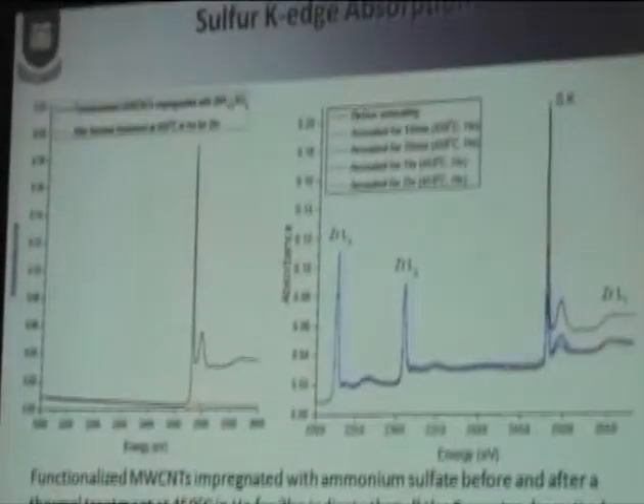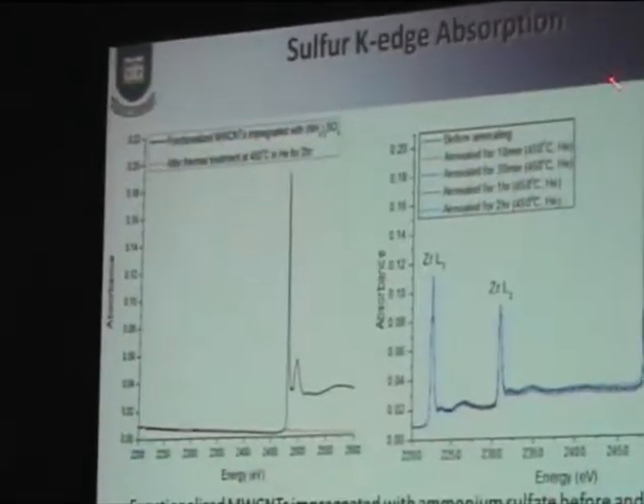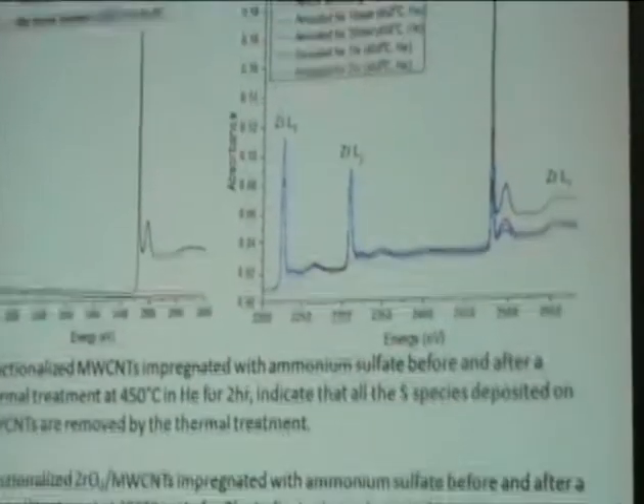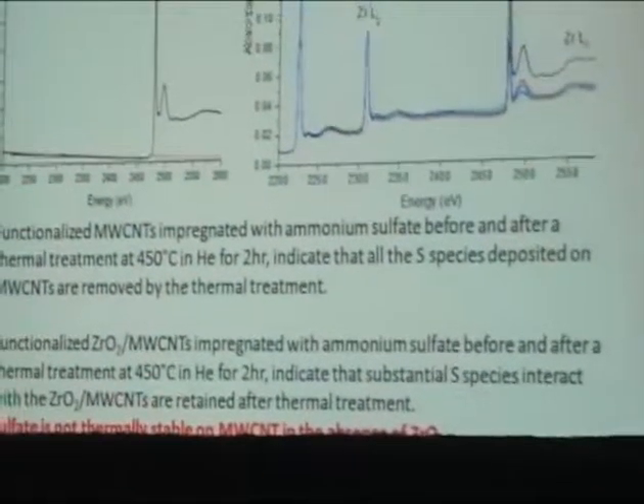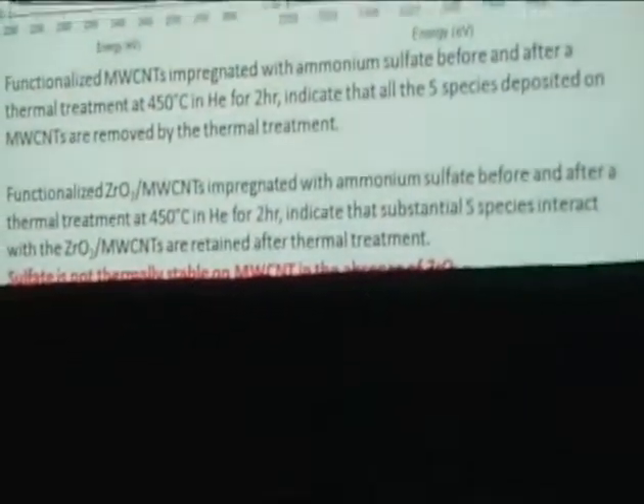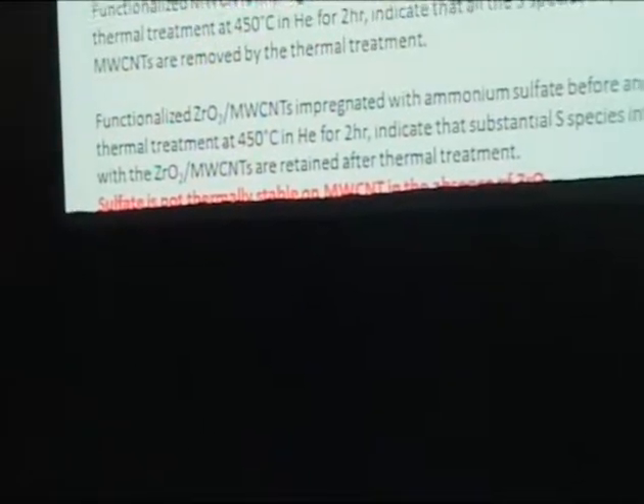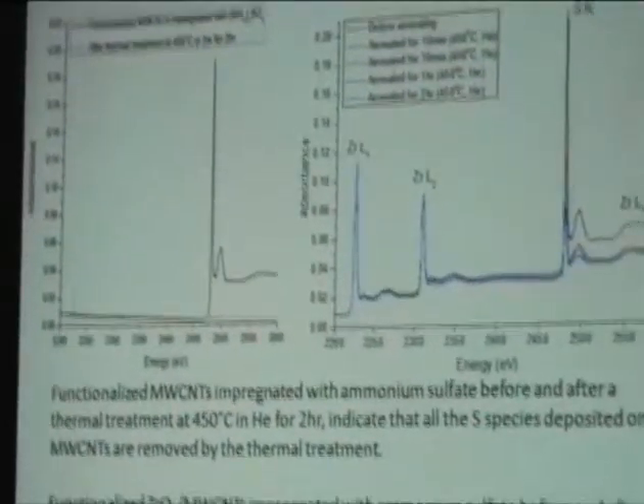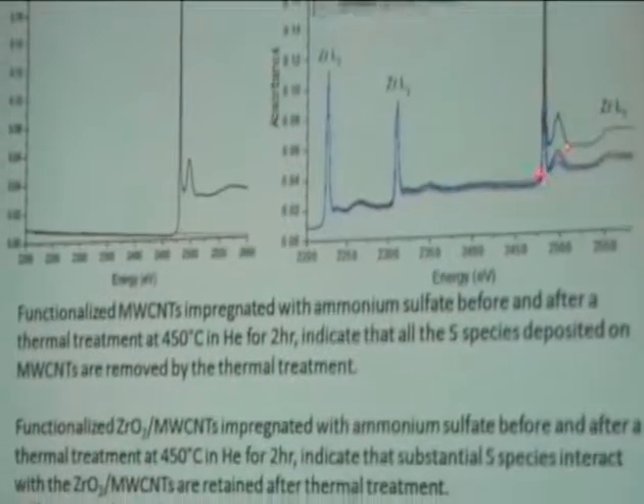Okay, next thing I'm going to do is go to the sulfur K edge, and initially we're doing something very simple here. We want to study the bonding of the sulfate to the zirconia. It could be made more complex if it was also binding the carbon edge, but it doesn't. So we put sulfate on carbon with no zirconia, and we get a strong signature of the sulfur. If we heat it to 450 in helium, all the sulfur decomposes and leaves the surface. But in the presence of zirconia, it does not all leave. Some of it interacts with it.